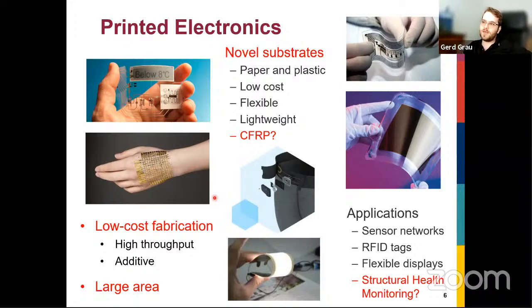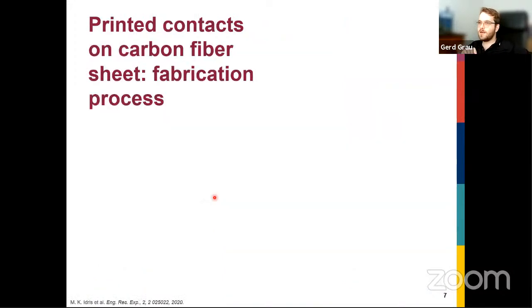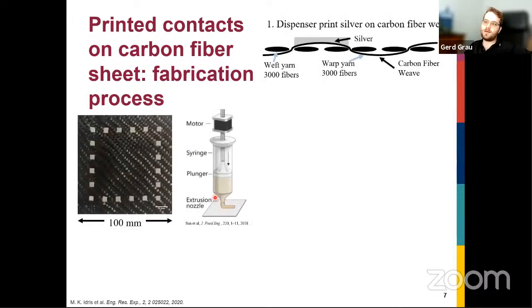And then the added benefit is the carbon fiber itself is electrically conductive, so we can actually use it as part of our system, for example, for sensing. So to do this, we developed a process to print a conductor onto a carbon fiber sheet. And what we do is we actually print on the dry carbon fiber textile. So before it's been infused with epoxy, that allows you to print onto a 2D structure, which is easier than onto a 3D structure. And we use paste extrusion or dispenser printing.